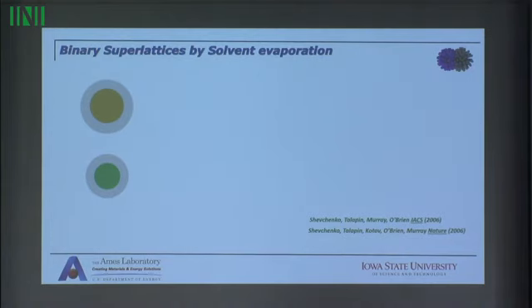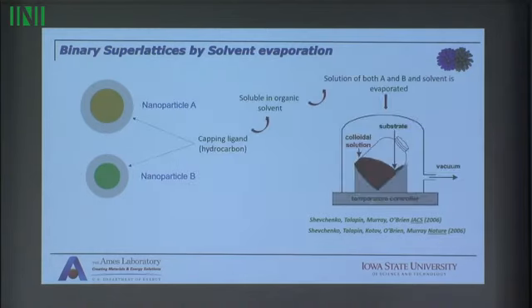So you have two types of nanocrystals, and they are functionalized with hydrocarbons, with alkyl thiolates, and you put them in solvent, on something that looks like that. Then you gradually evaporate the solvent, and at the end of the evaporation process, you are left with this particular structure. In this case, it is sodium zinc 13, which I already anticipated is one of my favorites.